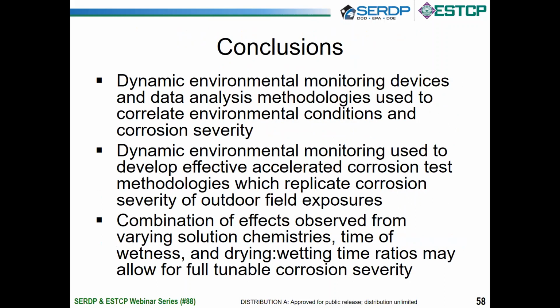Slide 58, please. So to wrap up, dynamic environmental monitoring devices, as well as data analysis methodologies, allow us to correlate environmental conditions and corrosion severity. Again, we did that with dynamic monitoring sensors, which capture temperature, relative humidity, and solution resistance, which allows us to much more accurately quantify the environmental exposure of any outdoor field exposure samples, so that we do a better job of replicating those same conditions during accelerated corrosion test development.